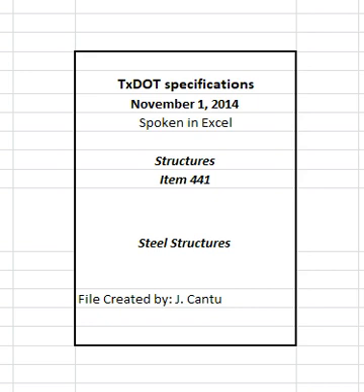3.2 Welding. 3.2.1 Details. 3.2.1.1 Rolled edges. Trim plates with rolled edges used for webs by thermal cutting. 3.2.1.2 Weld tabs. Use weld tabs at least 2 inches long for manual and semi-automatic processes, at least 3 inches long for automatic processes, and in all cases at least as long as the thickness of the material being welded. Use longer weld tabs as required for satisfactory work.